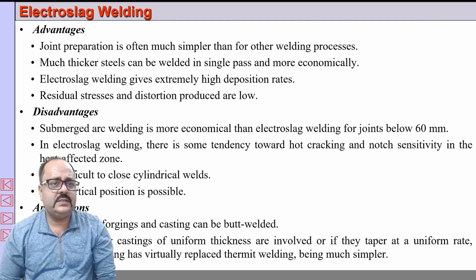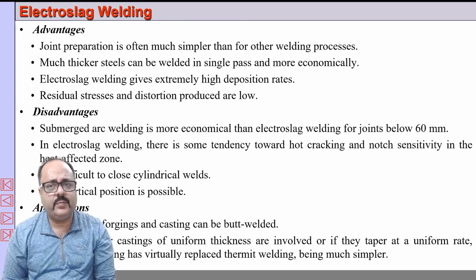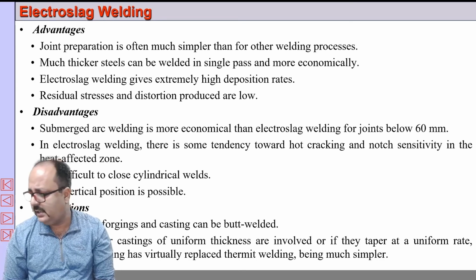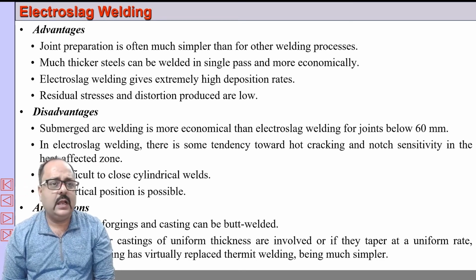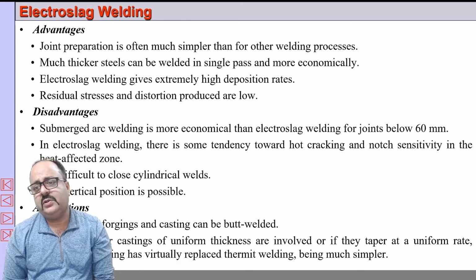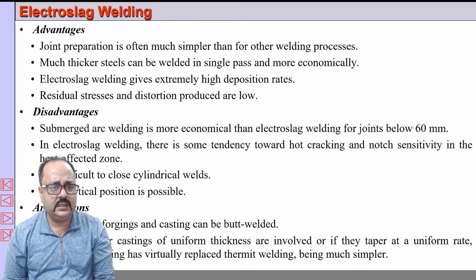So what are the advantages? It is simpler compared to other welding processes. Much thicker steels can be welded. Electroslag welding gives high deposition rates. Residual stresses and distortion produced are low. The disadvantage is that submerged arc welding is more economical than electroslag welding for joining below 60 mm. So if it is above 60 mm, definitely you can go for electroslag welding.